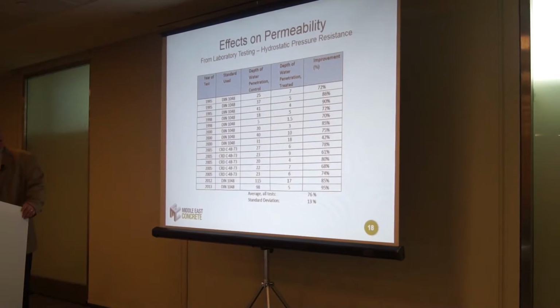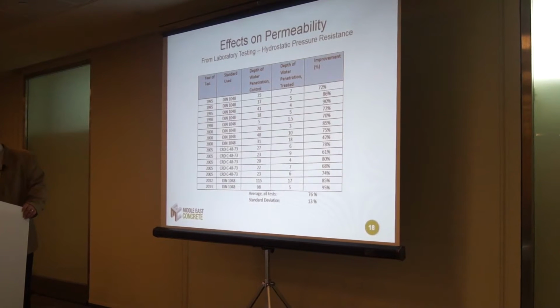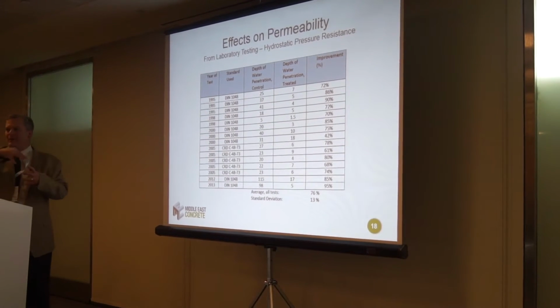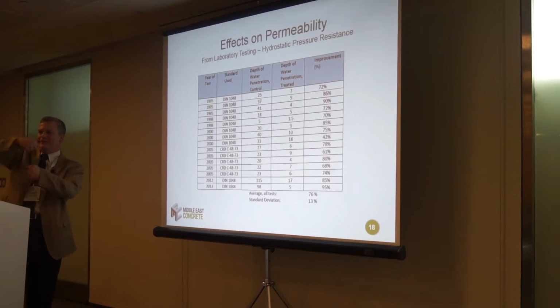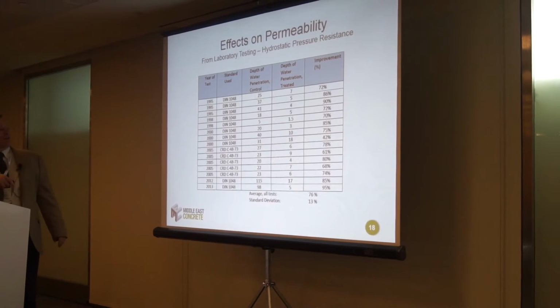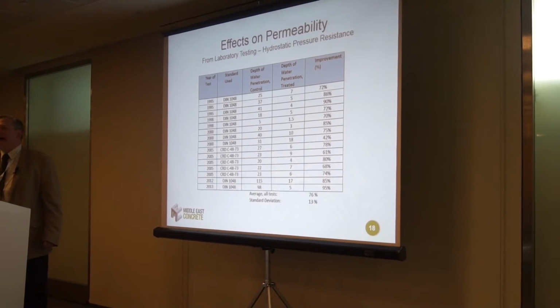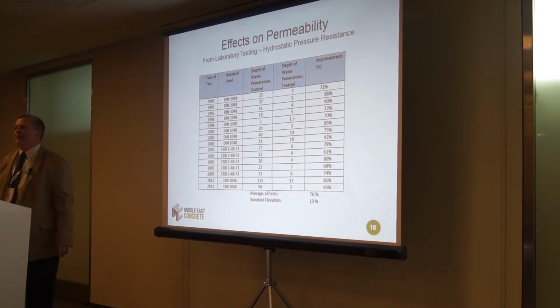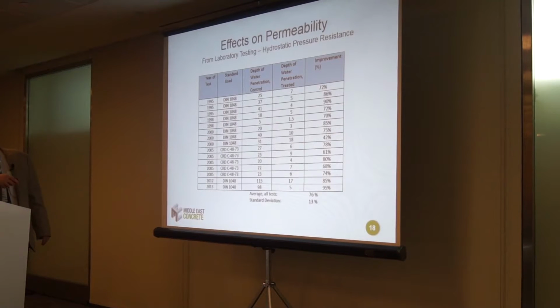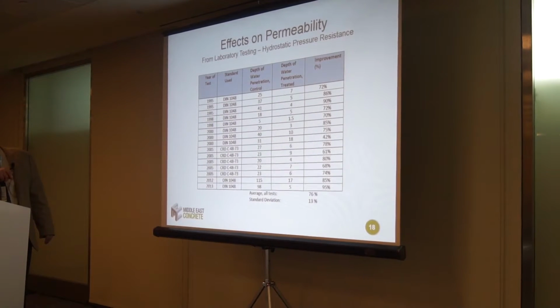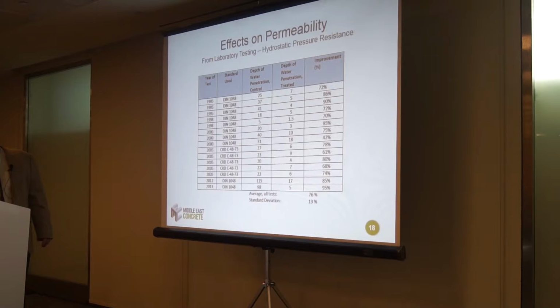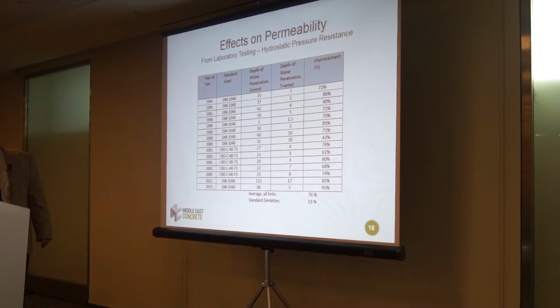This is the U.S. Army Corps of Engineers hydrostatic test. So all of these are DIN 1048 except for these. The only difference between the tests is that these are using pneumatic air to apply water pressure. So you have water and air pressure behind it. And the Army Corps of Engineers requires you to actually have a 100-foot column and drop the water into the concrete. So this is simulating the water column, and this is actually using the water column. The average of all these tests is a 76% improvement in hydrostatic pressure resistance. Standard deviation of about 13%.